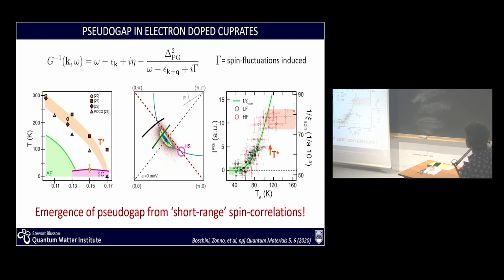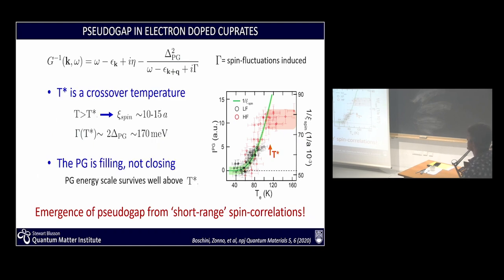Also, the temperature dependence seems to follow the green line here, and the green line is 1 over the spin correlation length. One can conclude from this a few important points. First of all, T star takes place when the spin correlation length, where we have no long range order, is less than 10 to 15 lattice sites. So that's when this takes place.